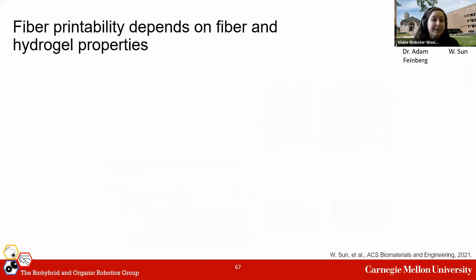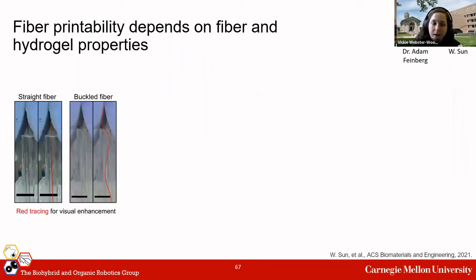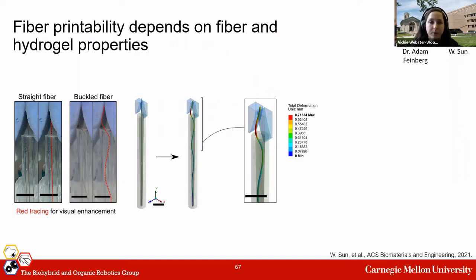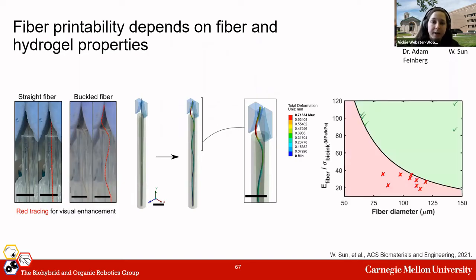Of course, as this process is essentially trying to push rope into jelly, the printability of any given fiber is going to depend on the fiber properties and the gel properties. If the gel is too stiff or the fiber is too compliant, then the fiber is going to buckle. So we developed both analytical and computational models of the printing process to allow us to provide a printability model for the process. And we validated this experimentally across a number of fiber types and sizes.